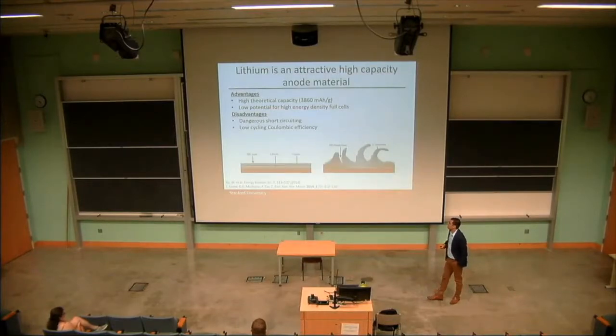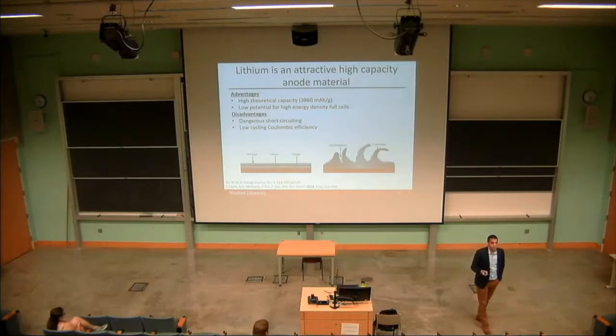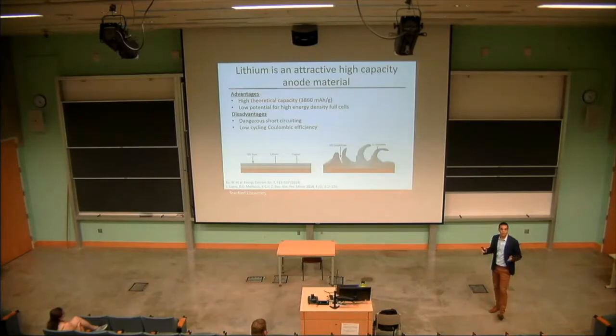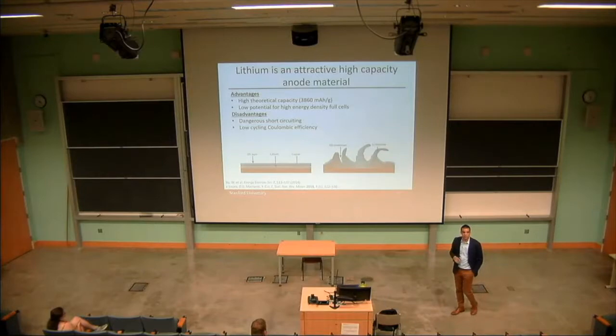And so lithium metal, again, has a very high theoretical capacity, more than 10 times that of graphite that's used commercially. Additionally, lithium is really beneficial because it's the reference potential for all of these battery systems, and so it's the lowest potential you could possibly achieve, giving you the highest voltage of a cell, depending on what your cathode is. So you really maximize your energy density when you're using lithium metal as your anode.